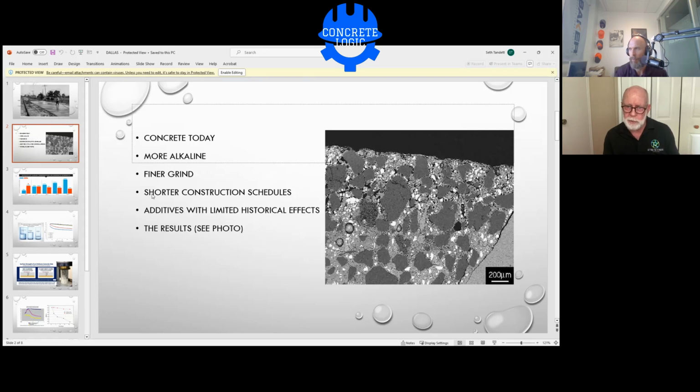Yeah, and it shows you the fallacy of what the moisture test will indicate, because there's this big reliance on RH probes, and the requirement is to sink the RH probes at least 2 inches into the concrete. We've completely bypassed the problem area. You're not going to get any information with that, because when you go deeper into the concrete, that's fairly stable, and that moisture content will remain that way for a long time, many years.